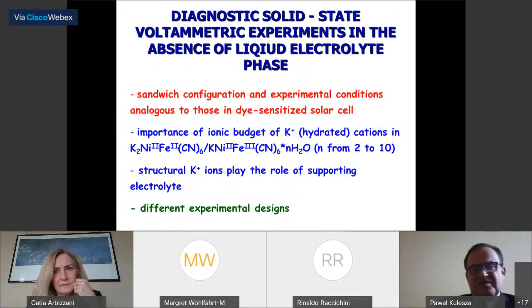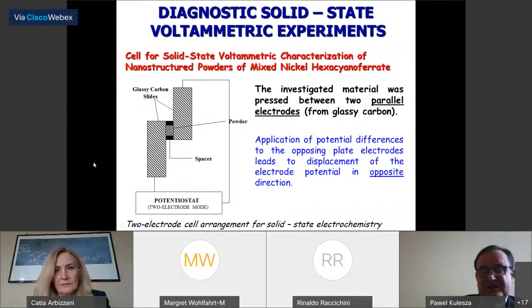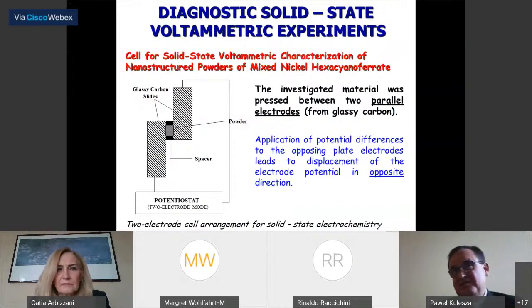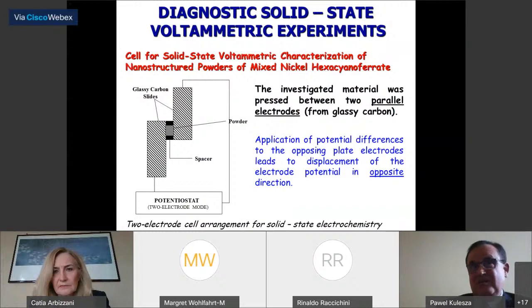But now we'll go to something which was not started with Roberto and the persons I mentioned, but later Iwona Rutkowska from our laboratory pursued research on using nickel hexacyanoferrate as a charge relay mode redox mediator. At that stage, we used mixed valent because there were two irons at two oxidation states. Well, the simple experiment would put it between two slides like a sandwich configuration and go back to the old electrochemistry.